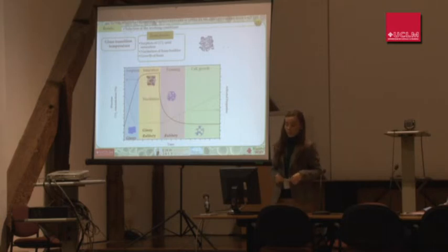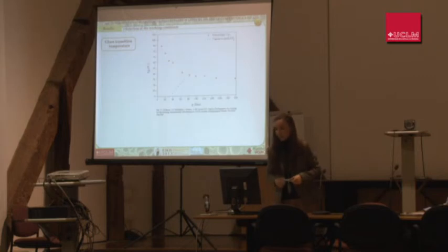The saturation of the foam should be carried out in a glassy or in a rubbery state, or at least near the Tg zone. When carbon dioxide is sorbed inside a polymer, it produces a high mobility of the polymer chain and consequently a decrease of the glass transition temperature. For this reason, we decided to determine the influence of carbon dioxide on the glass transition temperature of the polystyrene.